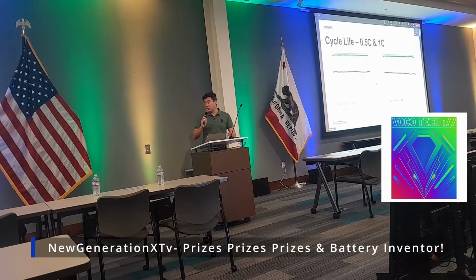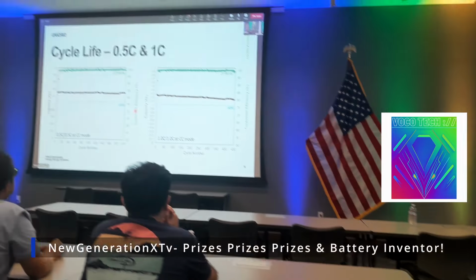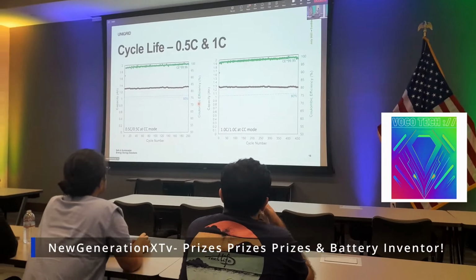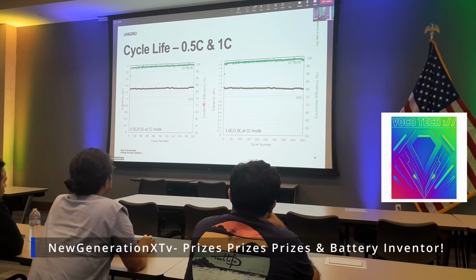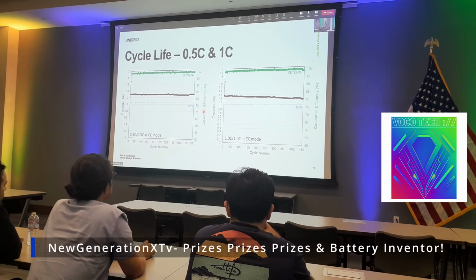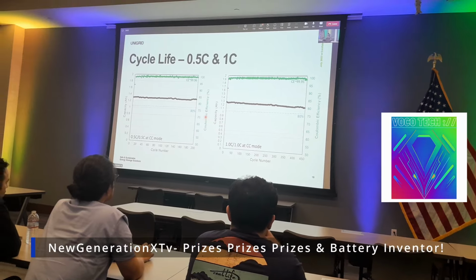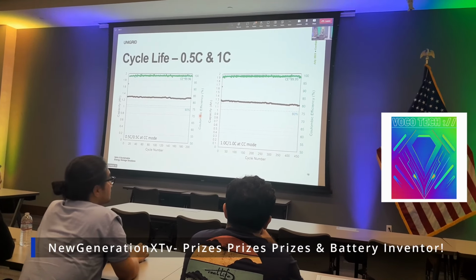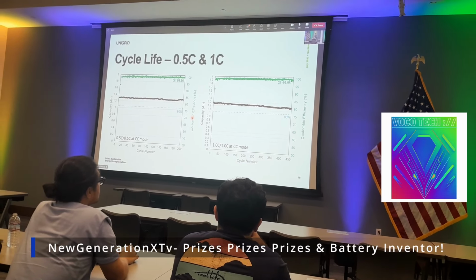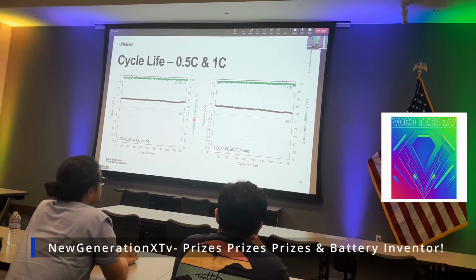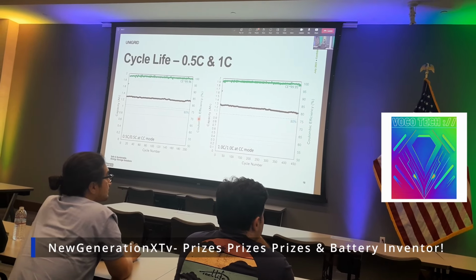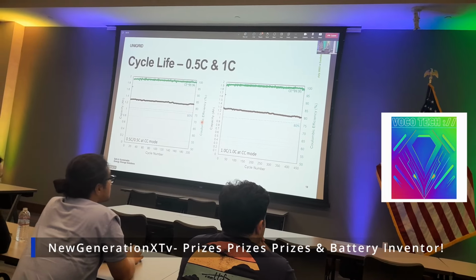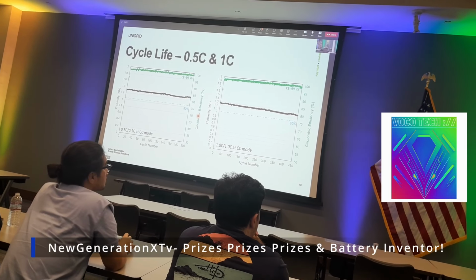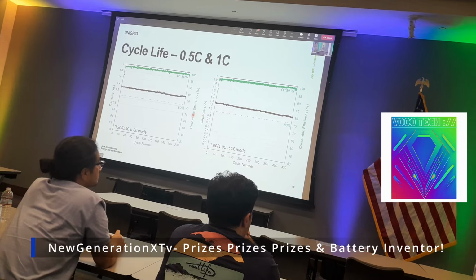So we started cycle life testing a couple months ago. We ran a half C and 1 C, which means each cycle is 2 hours or 1 hour. We've hit about, today the latest data is about 600-700 cycles so far. The industry standard for a home battery is about 2,000 to 3,000 cycles. That takes about a year and a half of testing. So we need more time to get there.